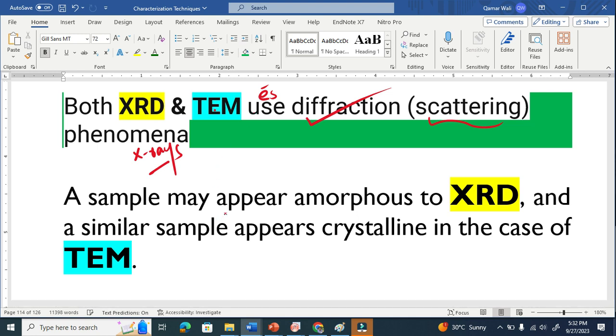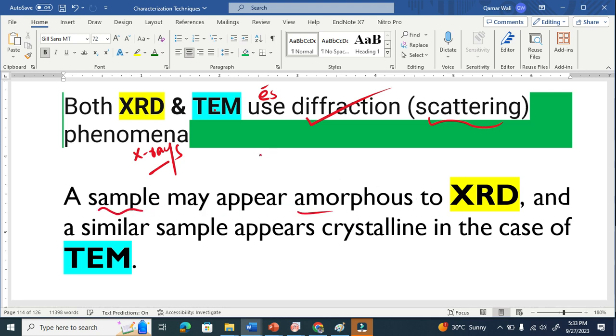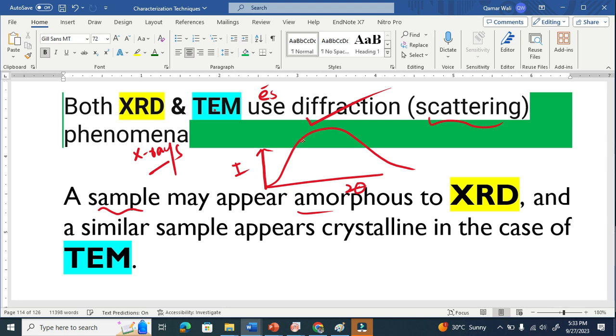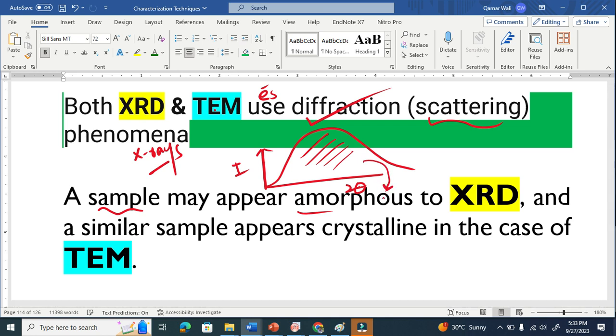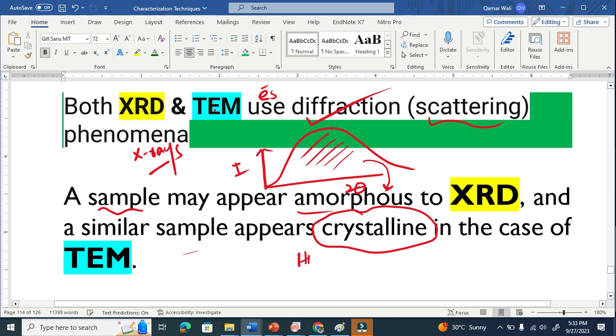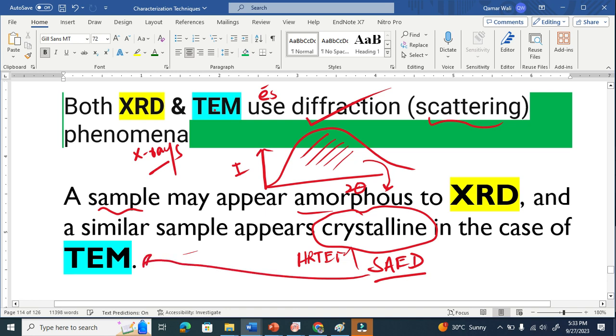The second reason is very important. A sample may appear amorphous to XRD — for example, we may get a broad peak on the two-theta versus intensity plot, indicating the material is amorphous. But once we perform TEM analysis, that same sample may appear crystalline. We know this from high-resolution images and from selected area electron diffraction, which is embedded in TEM. From there we see diffraction spots or clear rings, and we say the material is crystalline.